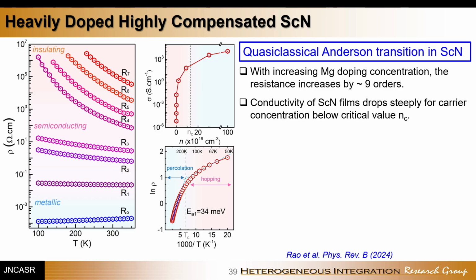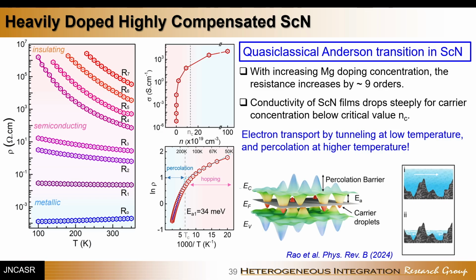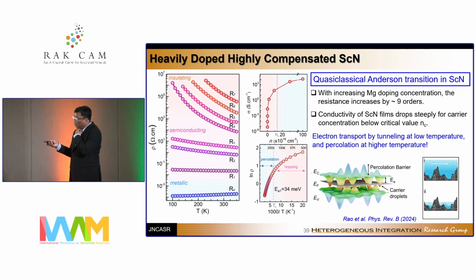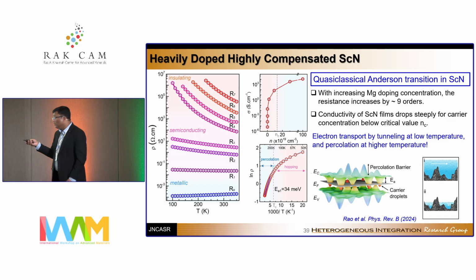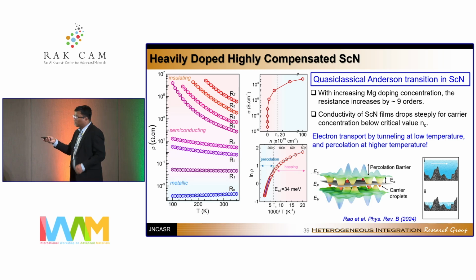And this is basically shown in this particular case as room temperature conductivity versus carrier concentration. And this purely happens because of the potential fluctuation induced carrier localization in this material. So at low temperature, if we take log rho versus 1 over T, the transport is primarily hopping or tunneling, but at high temperature, the transport is mainly governed by the percolation of carriers over the top of the barrier.